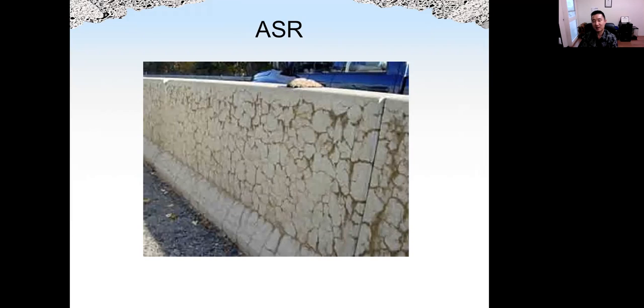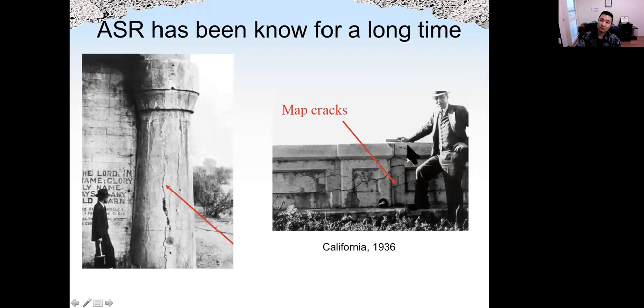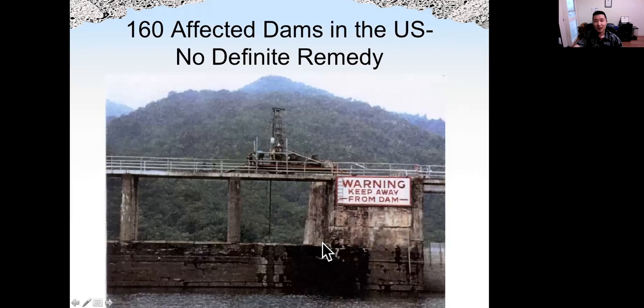That makes ASR very difficult to control. ASR has been known for a long time. The first ASR was found around 80 years ago in California. So in the US, we have hundreds of affected dams caused by ASR. If ASR happens, it is almost impossible to repair because again, ASR is generated within.